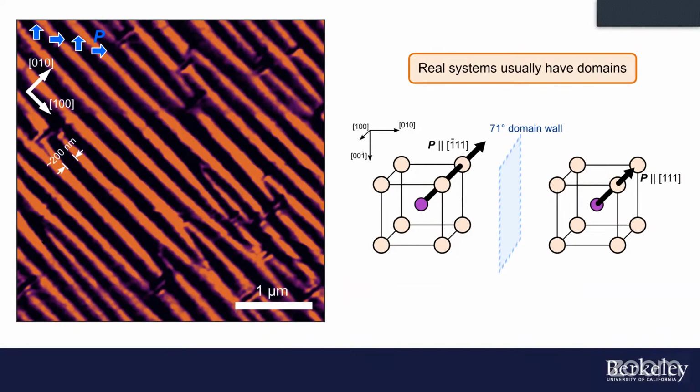And this domain pattern comes from the epitaxial strain that's induced by the substrate. So the substrate we deposit this material on is called dysprosium scandate. DSO gives it about a 0.5% compressive strain onto the film, so it squeezes the film a little bit. And it's a little bit anisotropic, which creates the preferred direction for these domain modes. Now, these domains